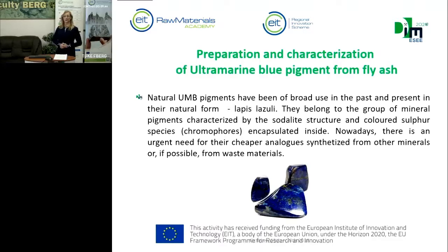Natural ultramarine blue pigments have been of broad use in the past and present in their natural form, lapis lazuli. They belong to the group of mineral pigments characterized by the sodalite structure and colored sulfur species, chromophores, encapsulated inside. Nowadays, there is an urgent need for cheaper analogues synthesized from other minerals, or if possible from waste materials. We tried to prepare these ultramarine